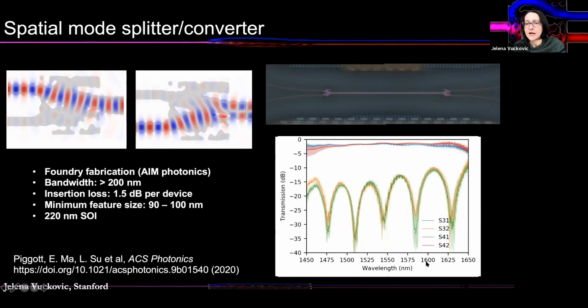It's a very large bandwidth. The operation bandwidth is about 200 nanometers, with very good contrast. You are not really routing your signal to the wrong port. That's what this contrast here means. And also the loss is 1.5 dB per device, which is comparable to the design where we predicted 1 dB per device. And that small difference comes from the fact that we thought that minimum feature sizes of 80 nanometers would work. And actually there were more around 100 nanometers. So there was a little bit of a difference there.